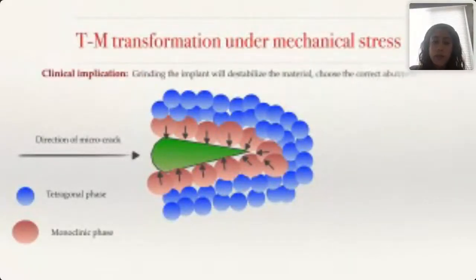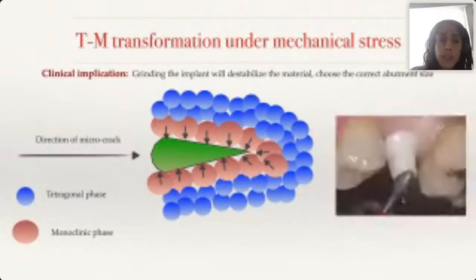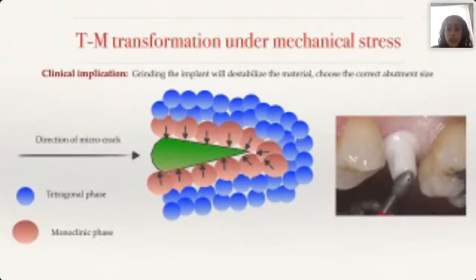These are tough materials, but one important point about this mechanical property is that we should try not to grind the implants as much as possible, because grinding induces transformations in the grains and microcrack formation that may destabilize the material. So the best approach is always to choose the right abutment size. Each company has different abutment sizes, short and long, so treatment plan the case beforehand. Make sure you have the right abutment size so we don't have to touch the implant or abutment surfaces — try not to grind.